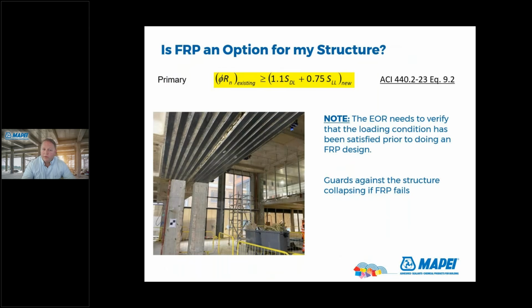So before you can even consider using FRP on your structure, there's a few things you need to look at. First, you need to make sure that the compressive strength of the concrete is above 2,500 PSI. If it's below that, FRP is not going to be a candidate for your structure. The other thing is the engineer of record is going to need to look at the primary or existing reinforcing that's in the concrete member and make sure that it is above this 1.1 service dead load plus the 0.75 service live load.